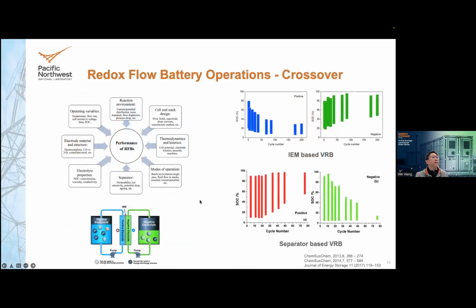In terms of flow battery operation, again, in Professor Wash's paper, there's a lot of good discussion on different factors that affect the performance of a redox flow battery. I will just talk a little bit about the crossover, since this is a phenomenon that is different from the lithium-ion battery. In a lithium-ion battery, you normally don't have active materials cross from one side to another. But crossover in the redox flow battery is a very common phenomenon because we don't have a perfect membrane that can separate the two sides of the electrolyte.